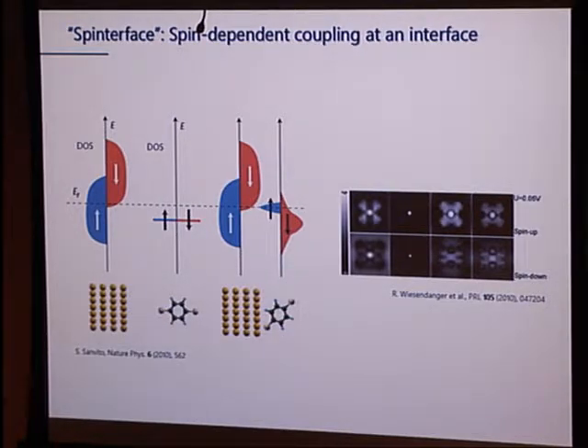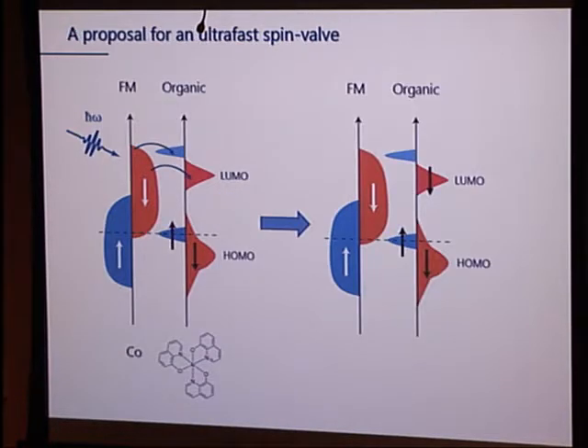So we saw this and we thought, if that's the case, perhaps we can use this to make an ultra-fast spin filter. So how would we do that? Here's the idea. Again, we have the spin split density of states on, say, cobalt, our ferromagnet. We have an organic, which has now in the valence band this density of states. And what we're going to do is populate the conduction band, if you prefer. We call it the LUMO, for lowest unoccupied molecular orbital. It's the same thing, by and large.